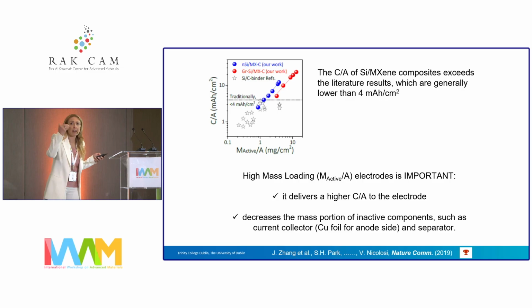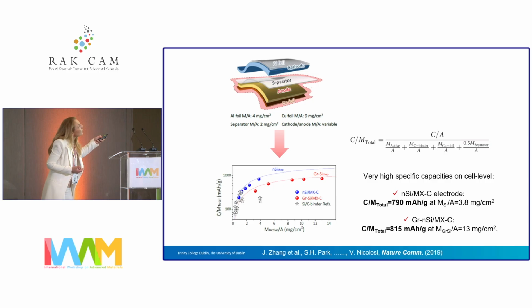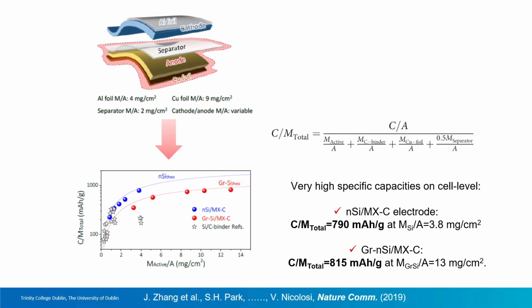So you deliver a very high areal capacity, and this becomes important because when you fully assemble a full cell, a full battery, it means that you actually decrease the portion of inactive materials, the portion of the current collector, for example, or the separator. And that's exactly what we did. We actually built full cells out of this, and indeed we could reach 700 or 800, even for the silicon capped with graphene, 800 milliamp hours per gram.